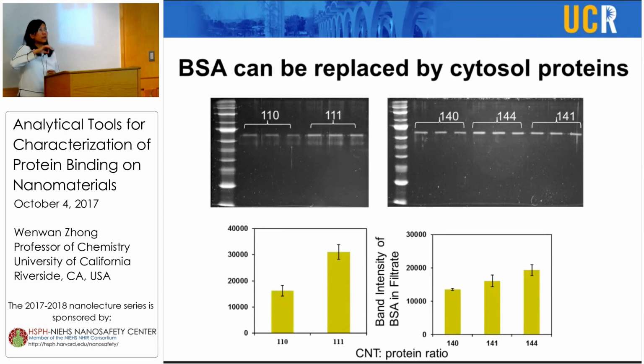Then we prepared the cytosol proteins to see how the cytosol protein can compete this BSA coating off, because it's not cross-linked, it's just non-covalent binding, right? So it's an absorption of the albumin onto the tube. So then in the cellular environment, because albumin concentration will be much lower, it will definitely be replaced by the cytosol proteins. But we see that with a thicker coating, of course less displacement will happen. All these numbers mean that the first number is the tube mass, the second number is the BSA mass, and the last number is the cytosol protein mass. So we see that with more cytosol proteins, a lot of BSA would be displaced from the surface and replaced by the cytosol proteins.